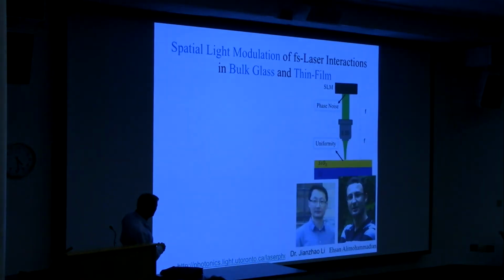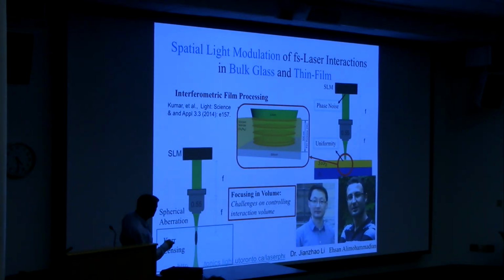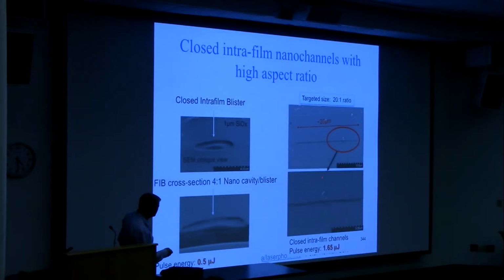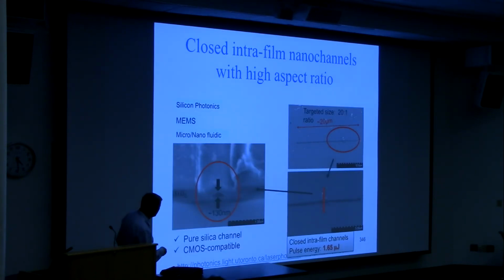And what I think is really important, going back to the shaped beams, is that Ehsan and Jianzhao working together have made a uniform line focus with this. And here's the structure. We're about 20 microns, pretty uniform now. What we are showing is that we can make nanofluidic structures, much smaller than the size of a cell. That's 130 nanometers high. And we're trying to run this tens of microns on the surface of silicon.